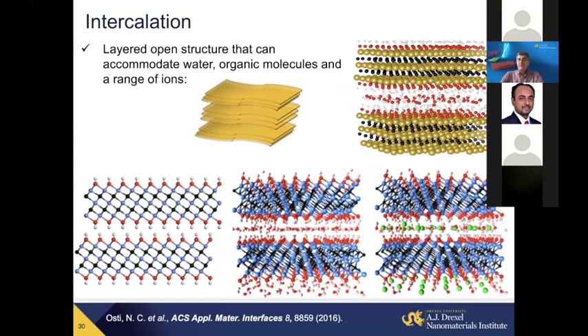And all these molecules will, on one hand, control interaction. On the other hand, those are quite strong, for example, the hydrogen bond between oxygen and OH terminated surfaces and this water. And even if you place it in vacuum, the water won't disappear by itself. So years ago, we showed that if you take carbide-derived carbons with extremely small pore size, there are always some molecules adsorbed in pores that allow dry friction without failure, because they will be released on the surface, providing a self-lubricating film. We believe similar behavior is possible in the case of MXenes.